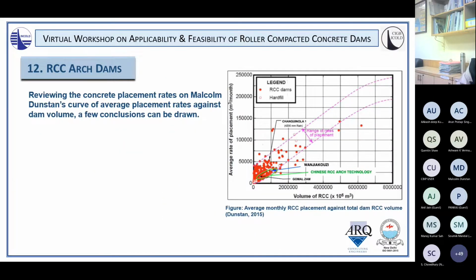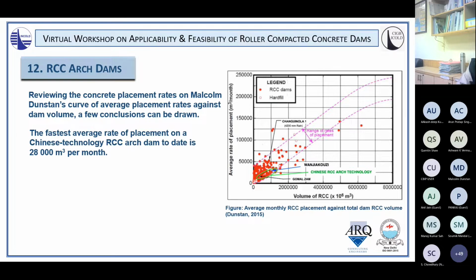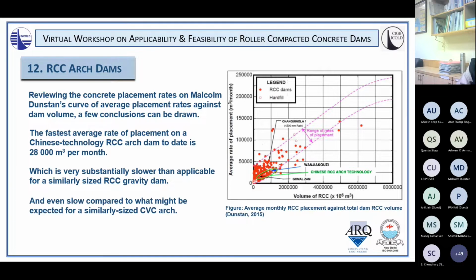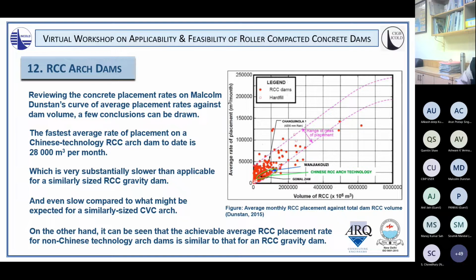So reviewing the concrete placement rates achieved for RCC arch dams, on the basis of Malcolm Dunstan's curve of average monthly rates of placement against total RCC volume, it's interesting to note that the fastest rate achieved in Chinese technology is 28,000 cubic meters per month, which is very substantially slower than applicable for a similarly sized RCC gravity dam, and it's even slow compared to what might be expected for a similarly sized conventional mass concrete arch dam.